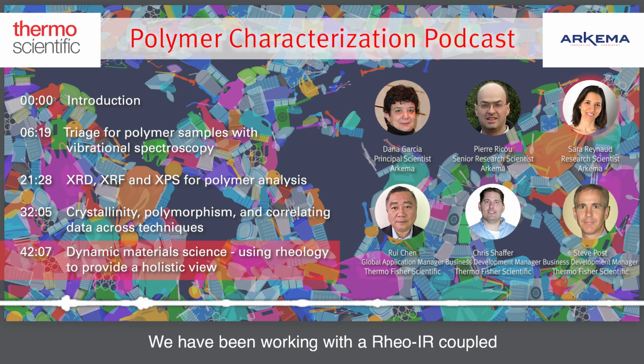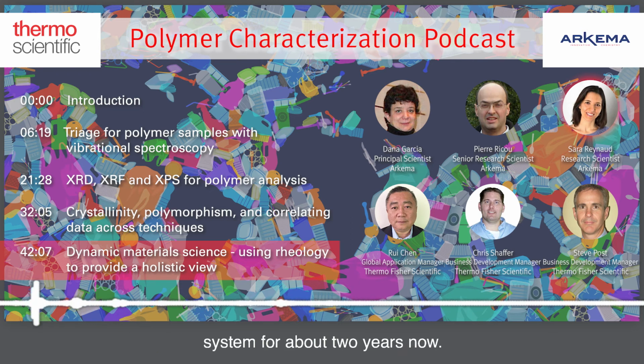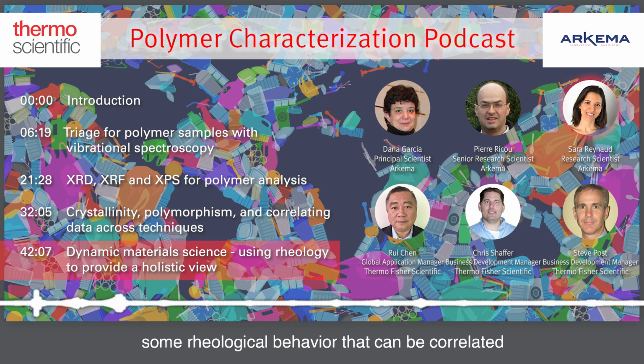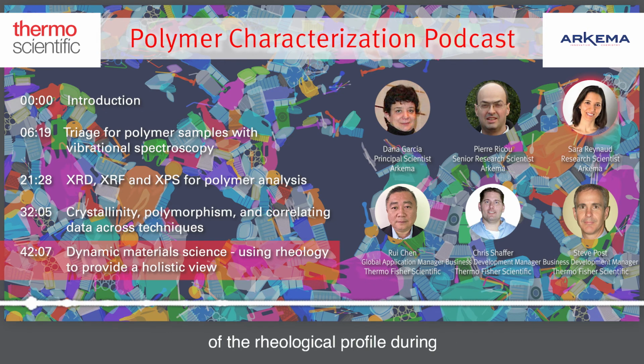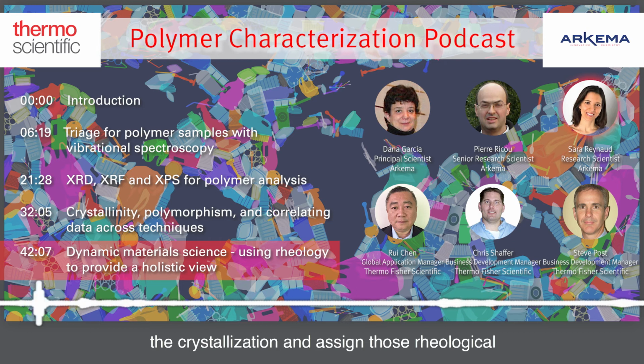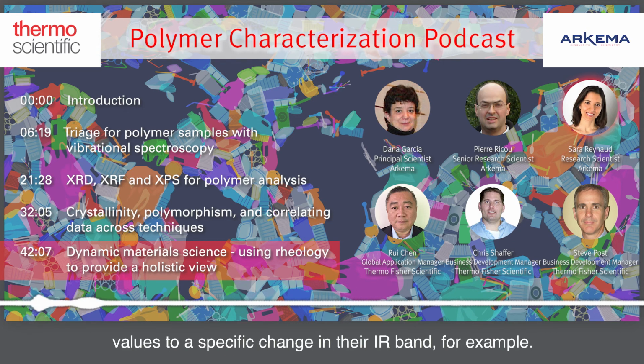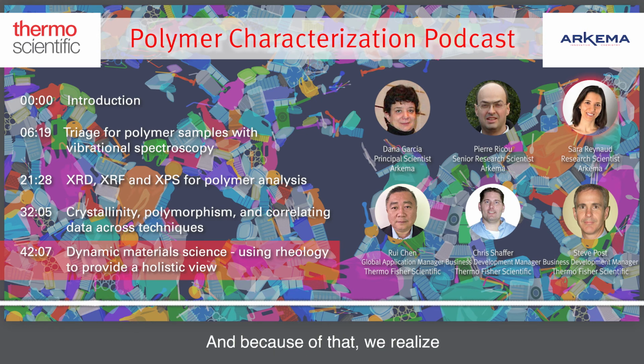So I should say that it's really amazing to see how many new avenues of interpretation this technology offered us. We have been working with the Rheo-IR coupled system for about 2 years now. We started to explore crystallization mechanisms and specifically some rheological behavior that can be correlated with the presence of intermediate structure. So we can now follow the evolution of the rheological profile during the crystallization and assign those rheological values to a specific change in the IR band, for example. Because of that, we realized that the mechanisms of nucleation and growth that are involved in our material are often much more complex than what we thought. So a lot of good learning came from synchronizing and combining those two powerful techniques together.